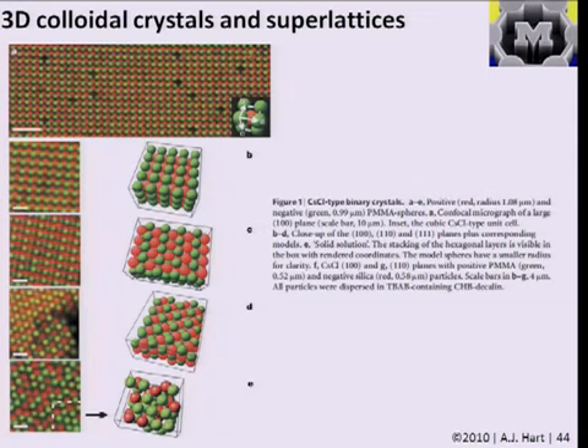So these are just schematically showing the ability to pack 2 different sizes of polymer particles. For example, taking 0.991 micron size PMMA polymer spheres and packing them with silica spheres that have a size that's slightly smaller, about 0.6 microns. And in fact, an additional aspect of the results shown here is that the particles had opposite charges. The fact that the PMMA particles were positively charged and the silica particles were negatively charged influenced their packing into what looks to us kind of like a crystal lattice. And we're just seeing them red and green in these actual images because they had coated them with fluorescent molecules that appeared red and green and let them view the packing in these individual cases.